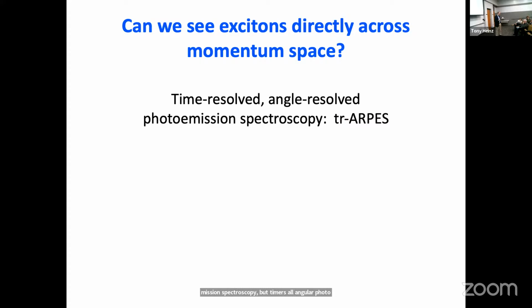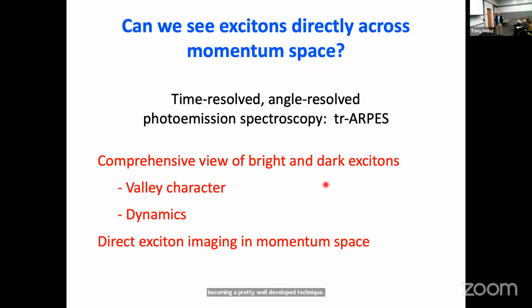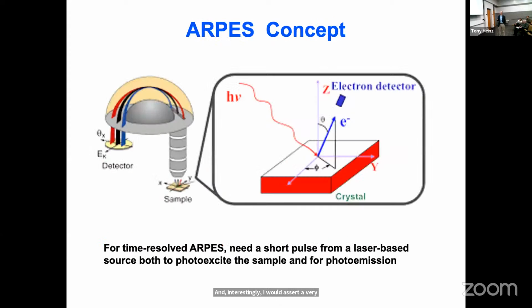So this is an interesting technique that has gone through various evolutions and I would say has been quite challenging experimentally, but with some of the advances, both in the electron analysis and collection and on the laser side, it's becoming a pretty well-developed technique. And in the context of what we're doing, it can give you a comprehensive picture of not only the optically bright, but also all the other dark excitons, their valley character, dynamics. And interestingly, I would assert a very direct imaging of the excitonic wave function. You'll see what I mean in a minute.